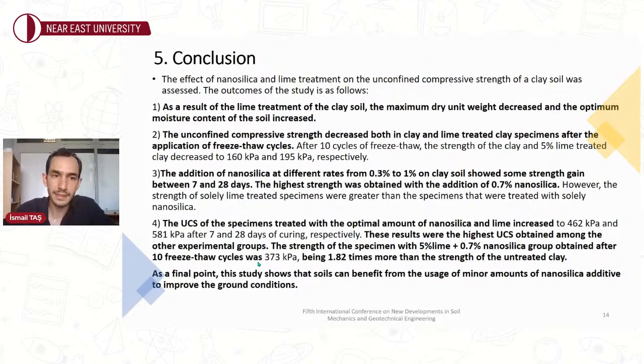First one, as a result of the lime treatment of the clay soil, the maximum dry unit weight decreased and the optimal moisture content of the soil increased. The unconfined compressive strength decreased in both clay and lime treated clay specimens after the application of freeze-thaw cycles. The addition of nanosilica at different rates from 0.3 to 1% on clay soil showed some strength gain between 7 and 28 days. The highest strength was obtained with the addition of 0.7% nanosilica.